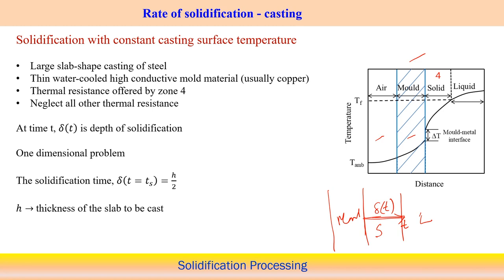Now, we can calculate the solidification time: when t equals Ts, the value of delta(t), the depth of the solidification, equals H by 2. H by 2 in the sense that, suppose this is a large slab shape casting. Here also it creates the delta T, and maybe this is the mold. So, both sides will have it, since heat transfer occurs from both sides. In that case, in the middle part, if the thickness of the casting equals H, this is H by 2, and this is also H by 2.